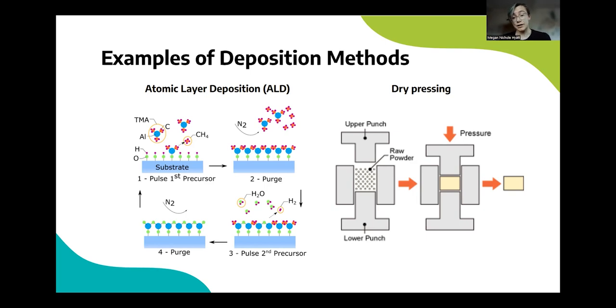Similarly, molecular layer deposition, or MLD, allows for both organic and inorganic molecules to be deposited in a similar manner. However, this method is extremely slow and therefore expensive. On the contrary, processes such as dry pressing allow for a much faster deposition, but the lack of control over synthesis conditions such as temperature and uniformity can greatly influence the formation of defects in the solid electrolyte, as well as alter the grain boundary morphology, or in other words, the layer interfaces.